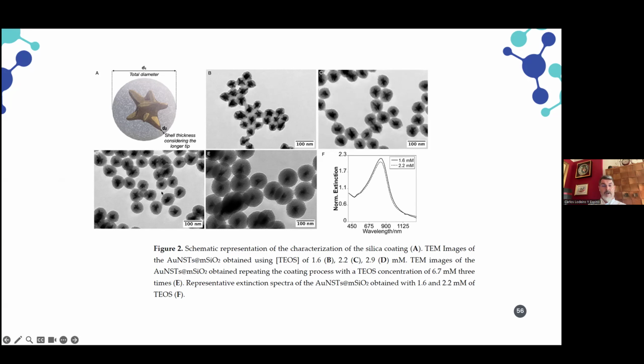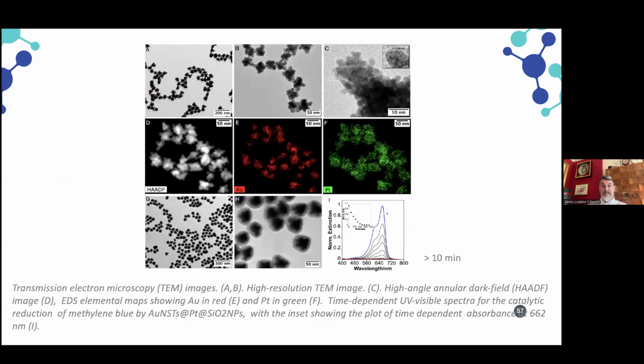We have added a novelty to these nanostars, in which we can protect them as well, as happened previously with the silver ones, with a layer of mesoporous silica or crystalline silica. You can see here the monodispersity, and the most important is the presence of just one nanostar inside each nanoparticle, maintaining the plasmonic band and the extinction coefficient. At this moment, we can create up to 1.5 liters of nanoparticles that are stable for more than 1 year on the bench without losing their catalytic properties.